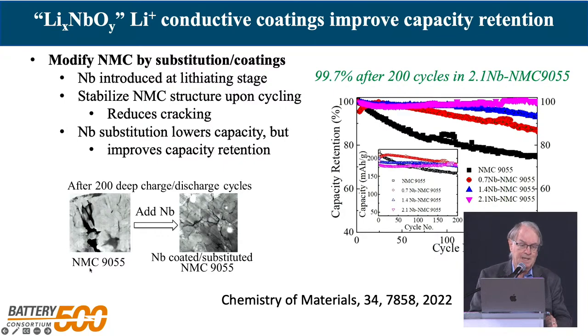So on the left-hand side, this is 90% nickel. You see we get these large cracks with 90% nickel, and with 2% niobium, we get some finer cracks, no big ones. So having the big cracks in here allows the solvent, the electrolyte, to react with the material and form another film on top. So we clearly got a message that we can both reduce the first cycle loss and improve the capacity retention using niobium.